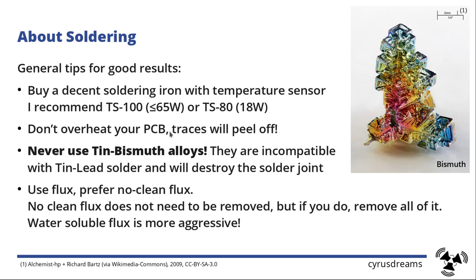If you are soldering, don't overheat your PCBs, because the PCB, as we already discussed, is a laminated structure, and the stickiness of the epoxy will reduce with temperature. Which means if you heat your PCB too long, your trace will peel off and your board is ruined. And you cannot get tin lead solder easily online or in shops anymore, because lead is toxic. It accumulates in your body if you inhale the fumes.